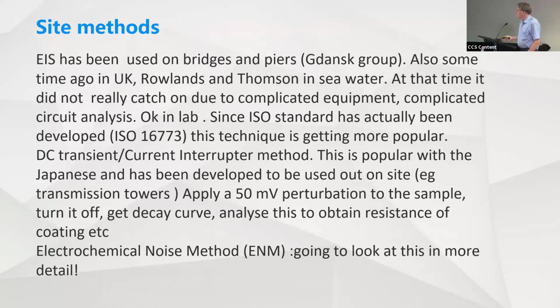So again, I've tended to be moving into interest in trying to get to a method that can be used in situ out on site. And that was done 20 or 30 years ago by Rowlands and Thomson, and the Gdansk group have done this with EIS. But the technique's getting more popular now because of the standard that's been produced on EIS. As we mentioned, the DC transient method, that's largely aimed at being used out on site. And what we're going to talk about today in more detail, and some application of it, is the electrochemical noise method.